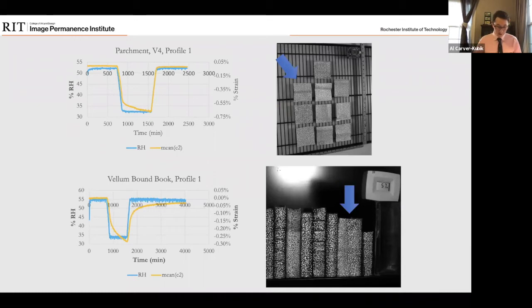Okay, so let's first look at the desorption profile where we started at 50% RH and decreased to 30%, 20%, and 10% RH. So shown here is DIC data that's represented as graphs. On the left-hand side of each graph is the percent RH, which is represented by the blue line. On the right of each graph is the mean percent strain, represented by the yellow line, that is the percentage of expansion and contraction. As the RH decreases, the material very quickly responds by contracting, and we see that as negative strain. The rate of contraction slows, and the material reaches moisture equilibration. Again, according to Fick's law, this is what we expect. It happens fast and then slows down.